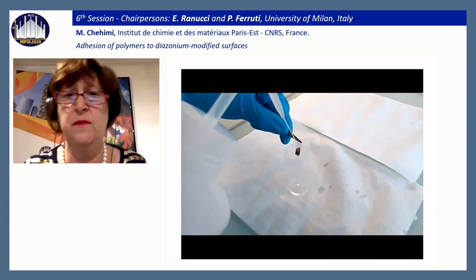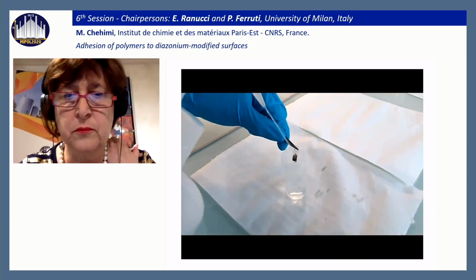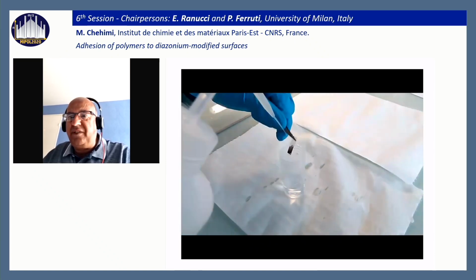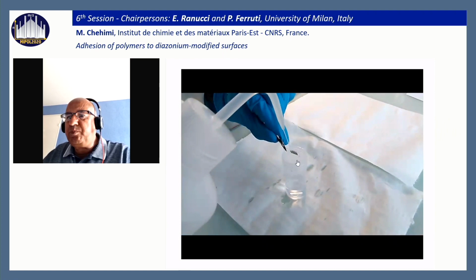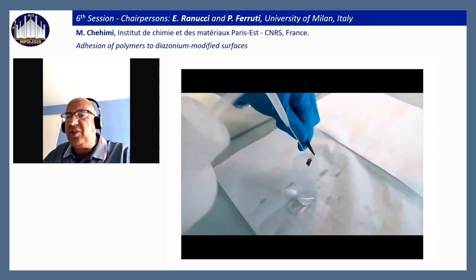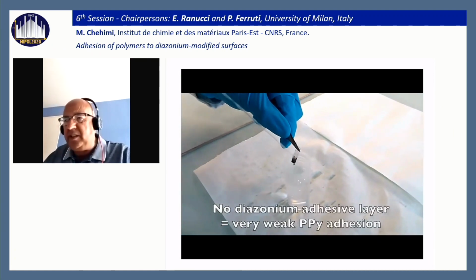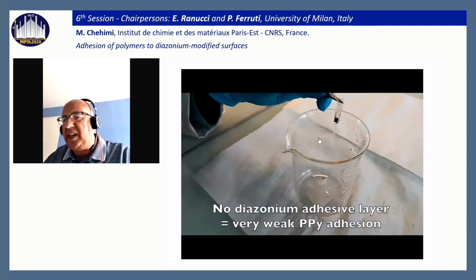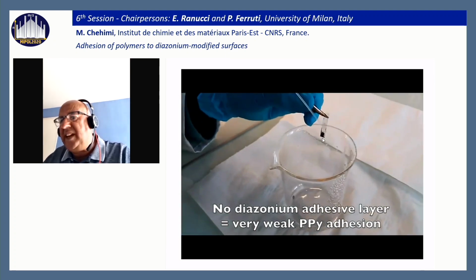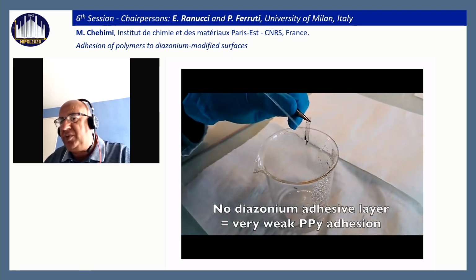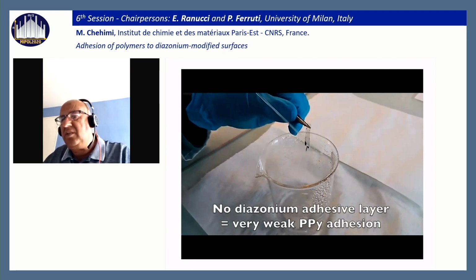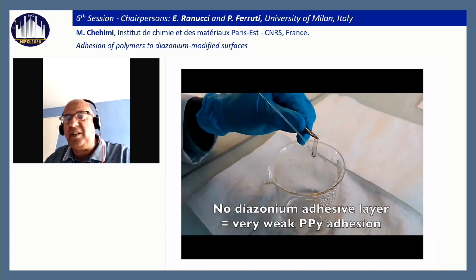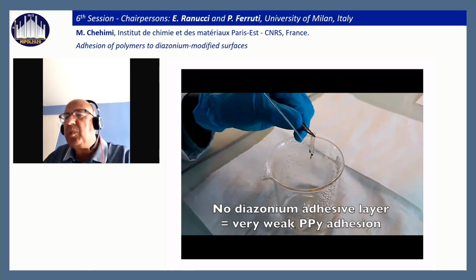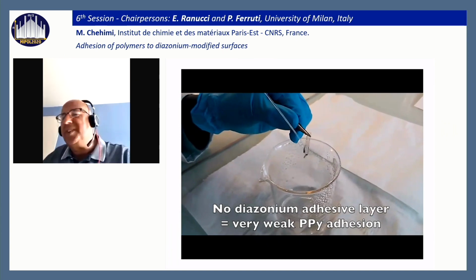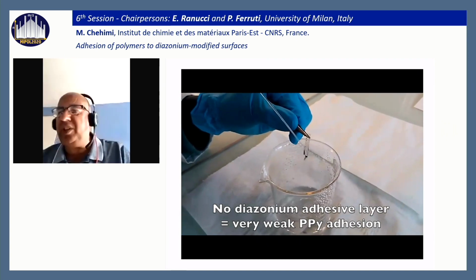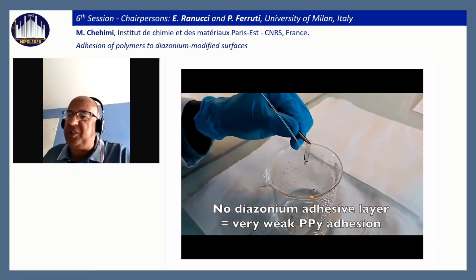Okay, so this is only a 1 minute video showing the adhesion of polypyrrole to unmodified and modified flexible ITO. This is on bare flexible ITO. You see, by washing, we can remove the conductive polymer very easily. And of course, some people in other conferences asked me if there is a test to measure adhesion.